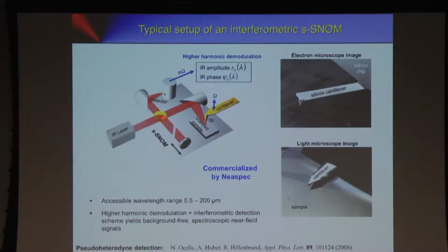Now we do this with the help of a Michelson interferometer. So we have here a reference beam. And this reference beam has several functions. First of all, it allows us a coherent detection. So we get amplitude and phase information. This is very important, and we can use it later on. If we come here with synchrotron or broadband radiation, we can use this setup as a Fourier transform spectrometer.